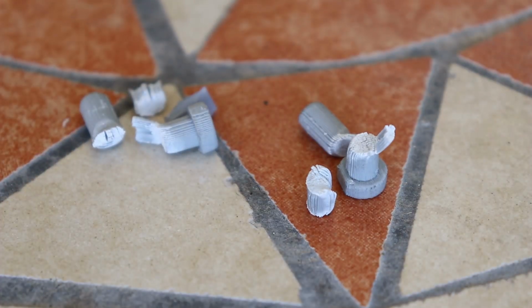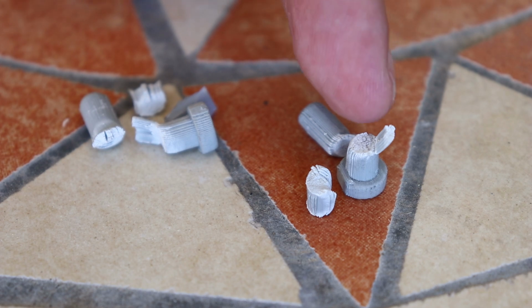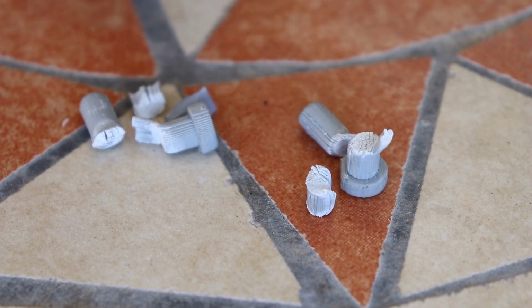And again I can see some marks of the weaker layer adhesion, so here and here you can see that layer detached. So definitely I think this should be printed at an even higher temperature, but I was already close to the maximum recommended printing temperature.